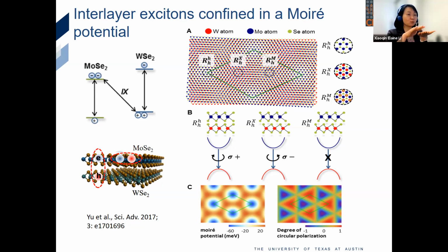What I'm trying to say is, we do not use photons resonant with the interlayer exciton to directly excite that dipole. Typically, we put carriers in above the gap, or we directly create an intralayer exciton. Then, because of band alignment, there is charge transfer and they form the interlayer exciton, and then they can recombine.